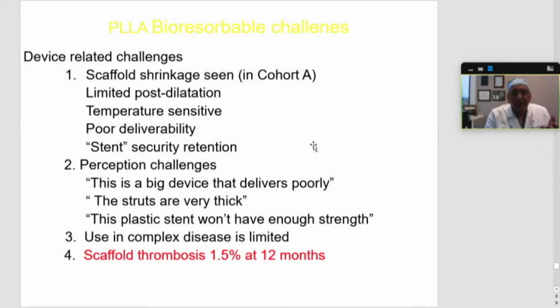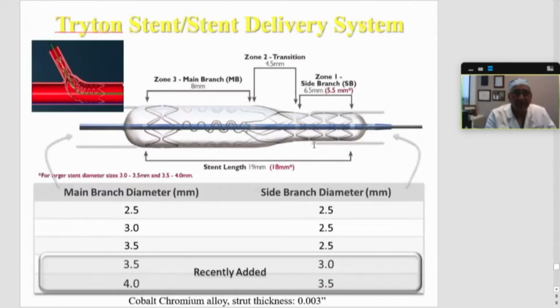Because there are several challenges which remain, right? I mean, we talked about shrinkage of the scaffold, but you have to worry about if I post dilate at a very high pressure, will it break the links, poor deliverability, and obviously stent security and retention. But then there are perception challenges. It's too big a device, it delivers poorly, the struts are very thick, the plastic stent won't have enough strength, and use in complex disease is limited, and scaffold thrombosis, as we have mentioned earlier, at 1.5%.